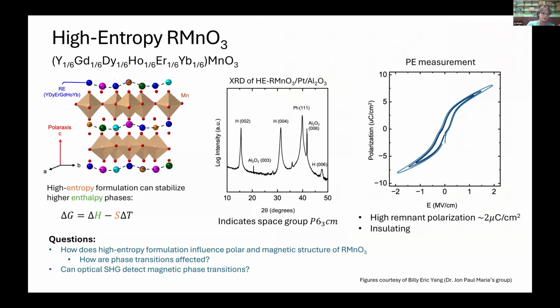The material that I got to work on is this high entropy manganite, where you have 6 different rare earth elements all in equal concentration on the R site. These high entropy materials are a new thing, and they're not super well understood, but people have been getting good results with them. The general principle is that if you crank up the S delta T term in your Gibbs free energy, this can counterbalance a higher delta H, and you can stabilize different phases than you would be able to otherwise.